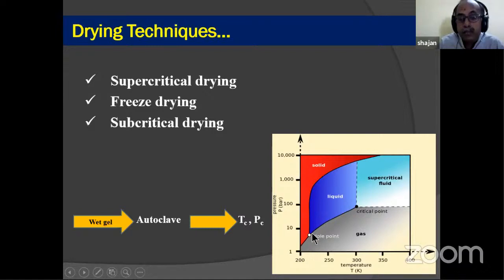So if you take this temperature pressure graph, and if you take this to this point, that is a critical point, it's a point at which the liquid is converted into a fluid. A fluid will have no surface tension. Surface tension is equal to 0. So it can easily flow out. So all the liquid or the solvent that is present inside the pores of the gel will be taken away. This is a very good method. And of course, we can say it's a perfect method to prepare aerogels.